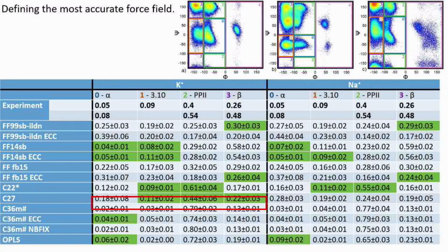And due to the fact that we simulated a lot of force fields, the most obvious question is, which force field is better? And we tried to check it. We compared our results to existing experimental results, which show the population of different conformations of the charged polyaspartic and polyglutamic acids. For each system, we plotted Ramachandran plots and divided them into different populations which relate to different conformations, and compared it with the experiment.